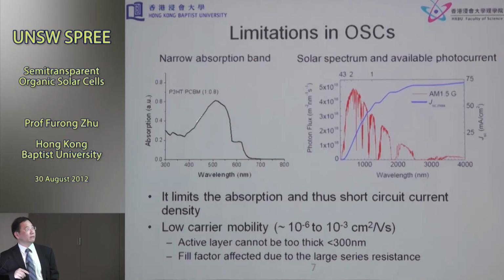So you can imagine that if the material only absorbs a small part of the light, there's a limitation in photocurrent generation. The other issue with organic semiconductors is that the carrier mobility is very low, a few orders of magnitude lower than that in inorganic semiconducting materials. This is another limiting factor for relatively poor performance. So in this field, synthesizing new materials is one of the challenges, and also because of this limitation, even though a material can absorb a lot of light, in reality the thickness of the active layer used in organic solar cells is typically less than 200 to 300 nanometers. Okay. So there are other issues.